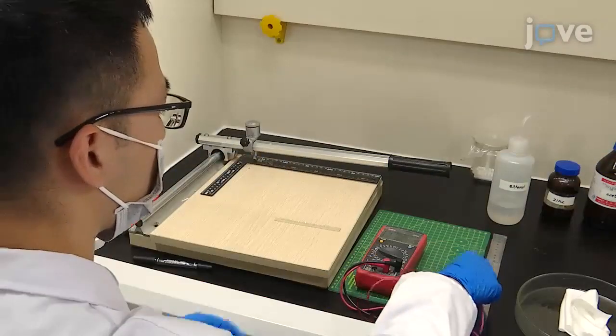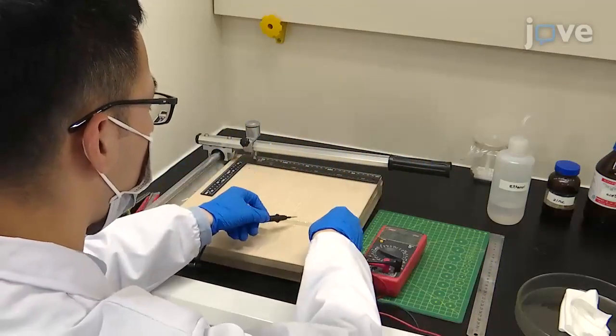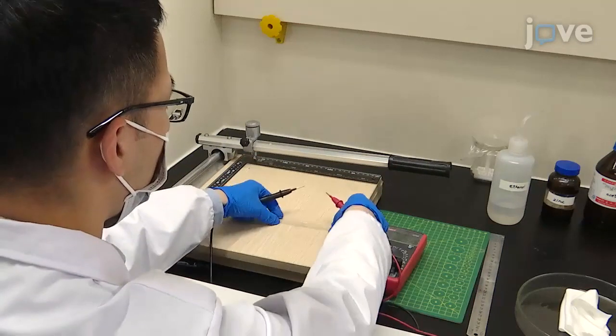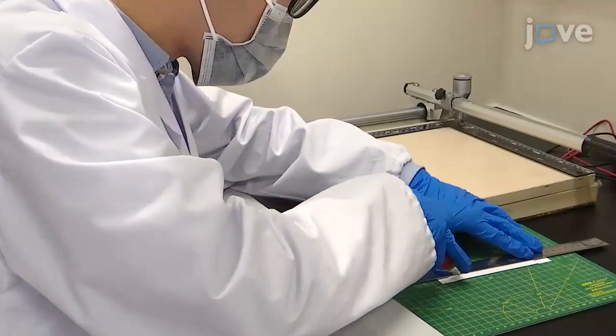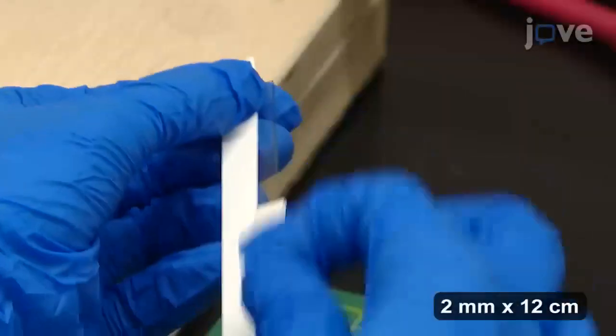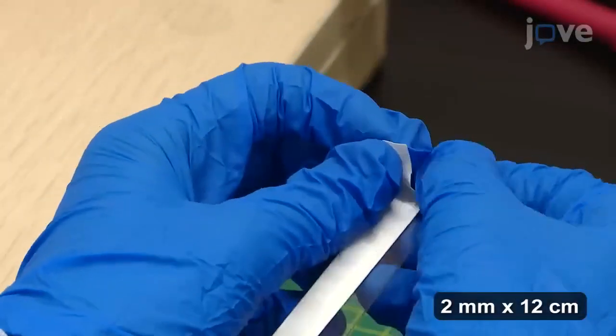Check the conductive side of the ITO glass for defects with a digital multimeter. Use standard adhesive tape to cover a 2 mm wide section lengthwise along the center of the ITO glass strip.